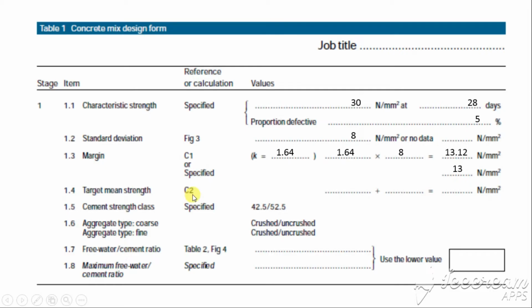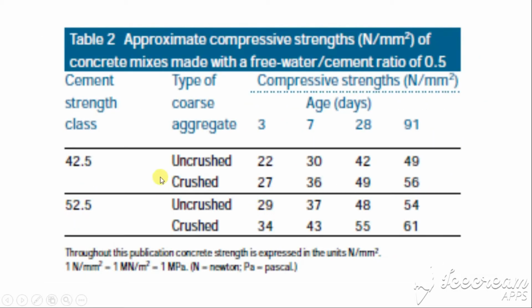And then for the target mean strength, refer to C2. Take the value of characteristic strength plus the margin. You will get 43 Newton per mm square. For the cement strength class, we specify 42.5. We get this from table 2 for 42.5, crushed aggregate, and for 28 days we get 49 Newton per mm square for the compressive strength. We will use this value to calculate the water cement ratio.